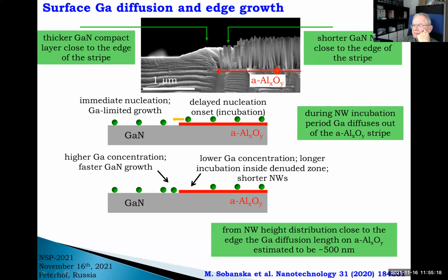Okay, in addition, we notice when studying the structure, have a look at this cross section. This is the aluminum oxide film. This is the compact layer, where there is additional extra edge growth on this part, while on the other side of the boundary, nanowires are thinner, shorter at the edge. And this tells us something about surface diffusion of gallium atoms.